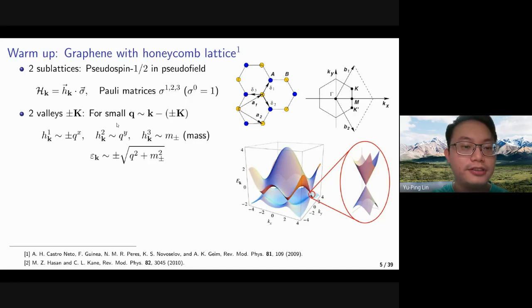And if we look closer to the two valleys, and with an infinitesimal q as the momentum deviation from plus minus K, we find that the h1 and h2 will become linear in the momentum deviation q. Meanwhile, the third component will be nearly a constant, and the low energy dispersion will look like this. So this will be linear if the mass vanishes, and it will be quadratic if the mass is finite, which corresponds to massless and massive conditions.